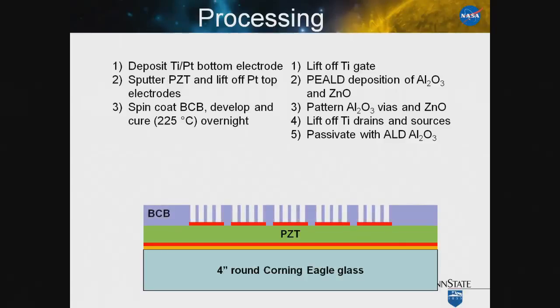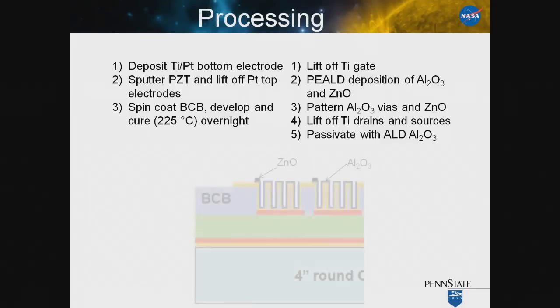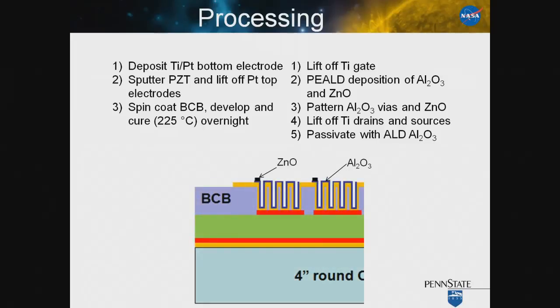There we go. So there is the benzocyclobutene, which has been photopatterned. On top of that, we deposited the titanium, and then using plasma-enhanced atomic layer deposition, deposit both the zinc oxide and the alumina dielectrics. Those are subsequently patterned by a conventional contact photolithography approach, and then we lift off the titanium sources and drains for those devices and ultimately passivate with the aluminum oxide.